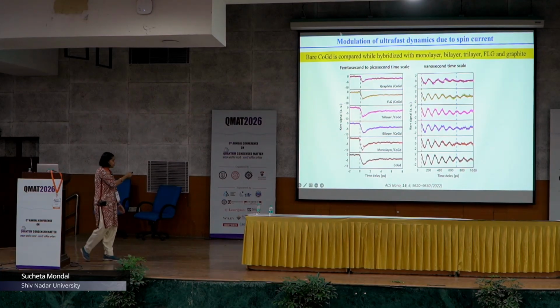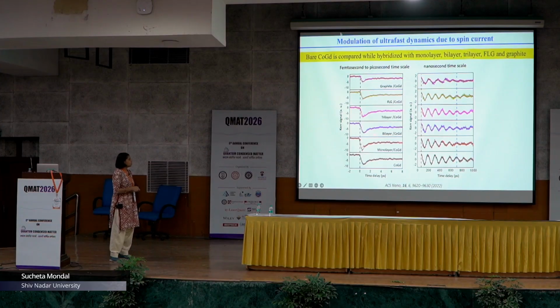So these are the time-resolved data. The left panel consists of the negative delay, then ultrafast demagnetization, and fast and slow demagnetization, and the right-hand side panel contains the precessional term. You see that this is the normal cobalt-gadolinium signal that I am supposed to get, and then when there is monolayer graphene attached to it, it is so fast. It is probably half of the demagnetization time that we are getting. So the dynamics is accelerated.